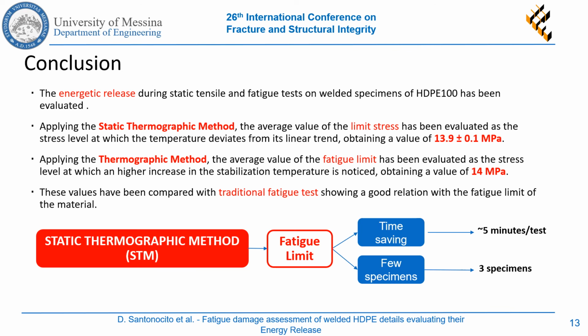In conclusion, in this work, the energy released during static tensile and fatigue tests on welded high-density polyethylene specimens has been evaluated. The infrared camera allowed the application of the static thermographic method and of the thermographic method, monitoring the specimen's surface temperature. By the static thermographic method, the average value of the limit stress has been evaluated as the stress level at which the temperature deviates from its linear trend, obtaining a value of 13.9 MPa. By the thermographic method, the fatigue limit has been evaluated as the first stress level for which higher stabilization temperatures are observed. Its value is equal to 14 MPa.